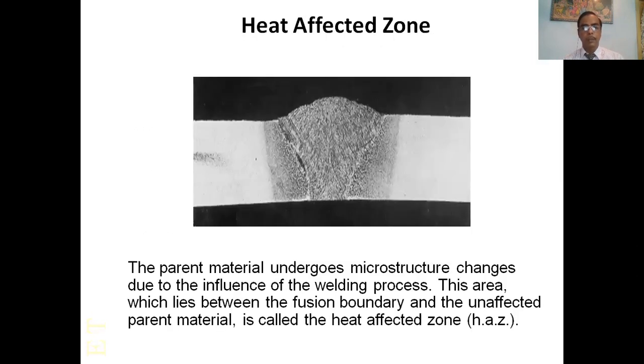Heat affected zone: the parent material undergoes microstructure change due to the influence of the welding process. This area, which lies between the fusion boundary and the unaffected parent metal, is called the heat affected zone. This is very important in welding. Less heat affected zone means good weld performance. The heat affected zone is detrimental to welding performance, but it cannot be avoided in fusion welding.